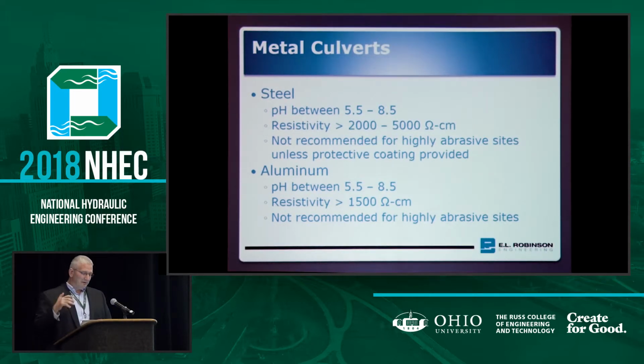As an example, if you're in one of those higher ranges of abrasion levels, a metal pipe, even like say if you were to use like a bituminous coated, you really need to be pretty close to neutral in your pH if you're at a very abrasive site, and it kind of works its way back from there. So if you have less abrasion, you can come down lower in your pH, but so it's kind of a balancing act. And when you're talking about how metal pipe works, resistivity is above about 2,000 to 5,000 ohm centimeters.